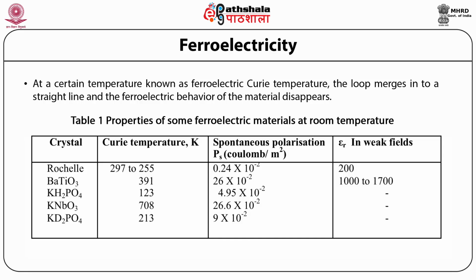So here we have a list of crystals, for example, Rochelle salt, BaTiO3, where the Curie temperature is 391, but for KD2PO4 or potassium niobate KNbO3, the Curie temperature is around 708 Kelvin. The spontaneous polarization PS in coulomb per meter square is also shown here, which is highest, of the order of 10 to the power minus 2, and is around 26 for BaTiO3, and which is less in Rochelle salt.